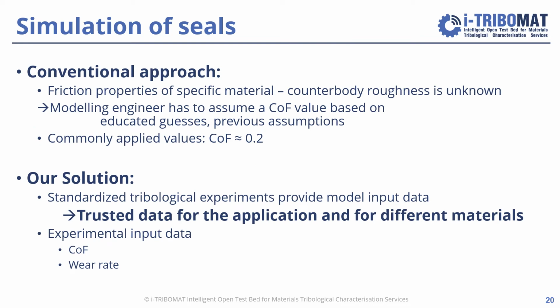So the next input value would be the coefficient of friction. The conventional approach is that you don't know the coefficient of friction between the counterbody and the specific material. You know qualitatively that the counterbody roughness is very critical, that the operating conditions can change it, but because you have no measured value, you're often forced as a simulation engineer to use educated guesses or go to some papers and use previous assumptions of another working group. So commonly values of around 0.2 are used, and this value is kept constant for all operating conditions and not changed for counterbody roughnesses, etc.